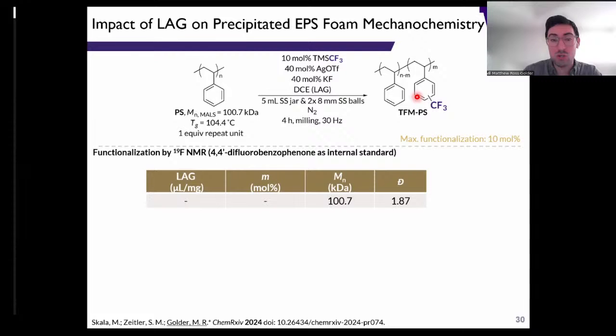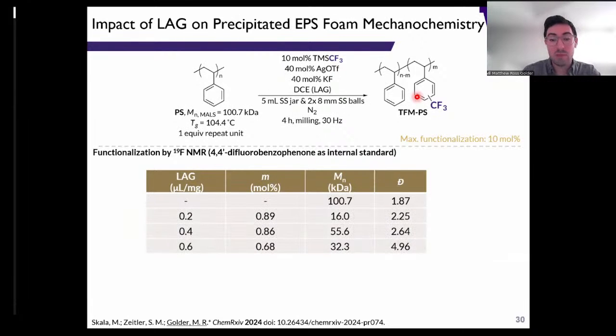So we can go through and change the amount of LAG solvent that we're adding. And we saw that if we add a small amount of LAG solvent, we get about 1 mol% tagging, which for things like ionic compatibilization is actually enough. Again, we don't need a lot of functionalization here to have a huge impact on some of the downstream applications and properties. But what I want to emphasize here is that we see this huge decrease in molar mass.